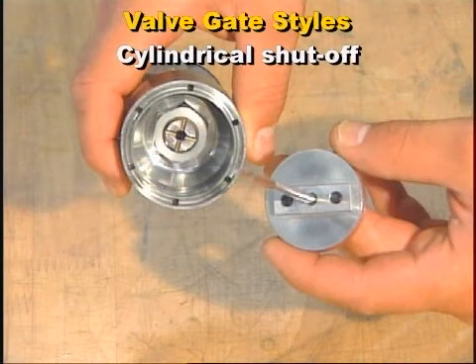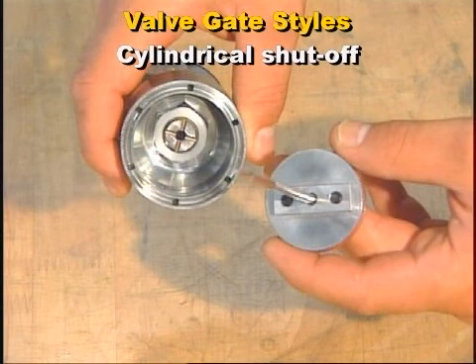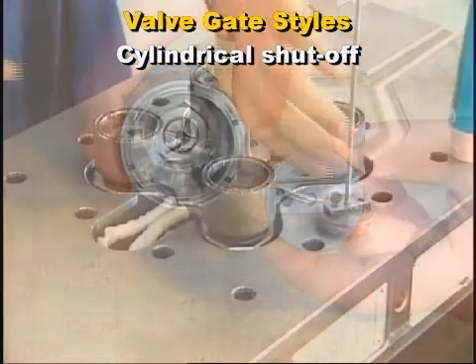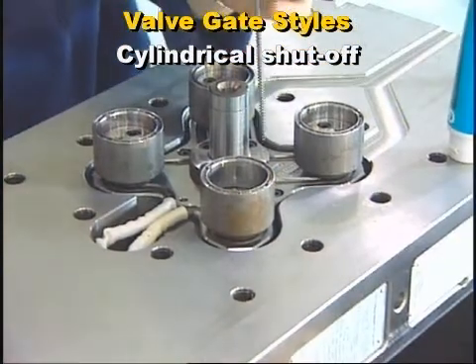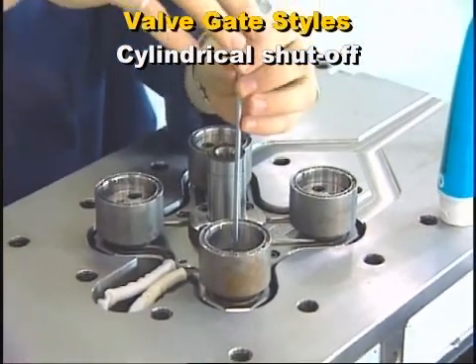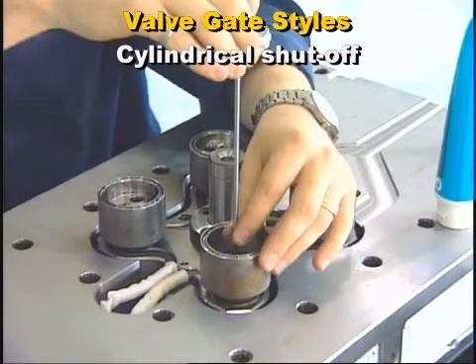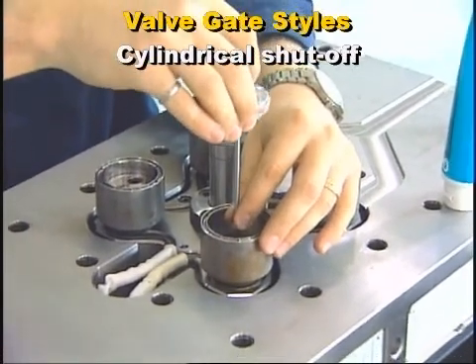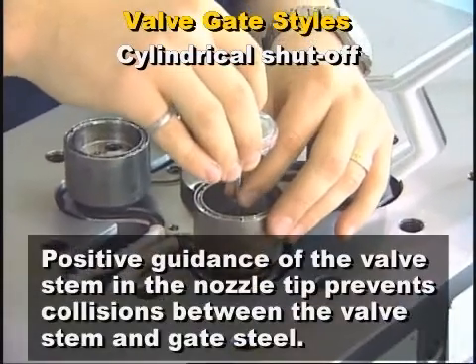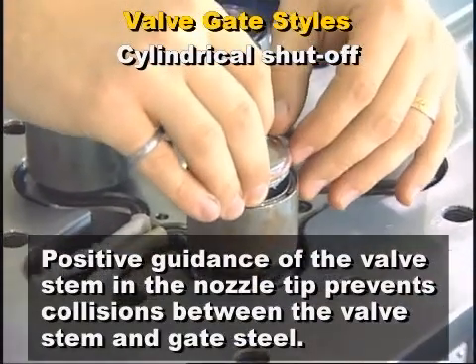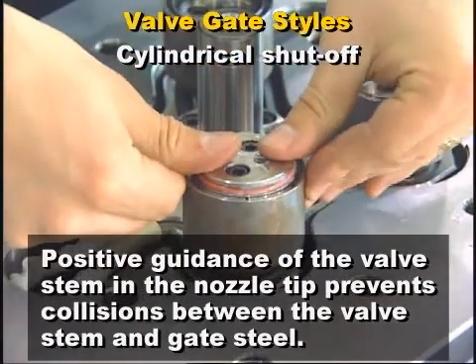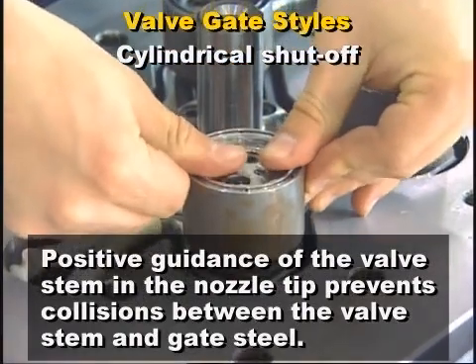The cylindrical sealing, however, is more sensitive to wear if the required tolerances are not maintained, causing rapid degradation in gate quality as the wear increases the size of the gap between the valve stem and the gate steel. Therefore, cylindrical seal valve gates require precise alignment of the valve stem to the gate in order to reduce wear. Ideally, positive guidance of the valve stem in the nozzle tip prevents collisions between the valve stem and gate steel.